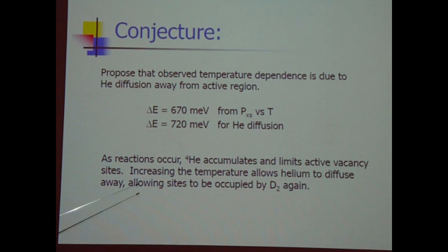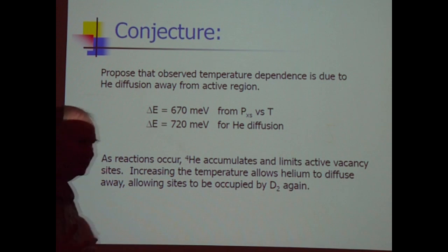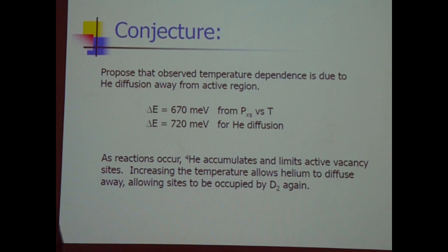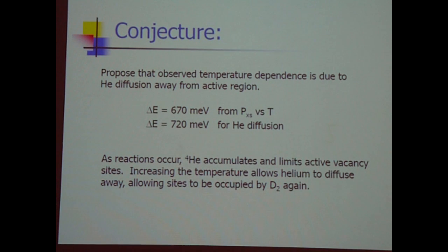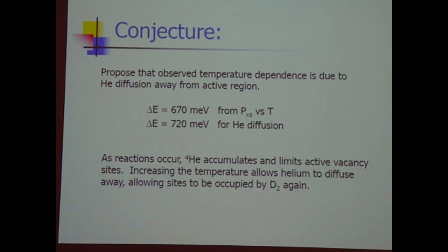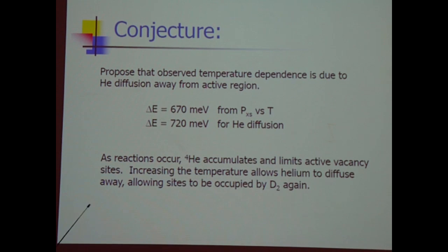So the conjecture here is that the temperature dependence could come about if you have a system that's working really, really well, so it's making so many reactions, it's making so much helium-4 that the helium-4 is plugging up all the vacancies. And then you're going to try to get the helium-4 out of the vacancy and then diffuse it towards the surface. So this also implies that getting it out of the trap initially doesn't take long relative to the diffusion time to a surface.